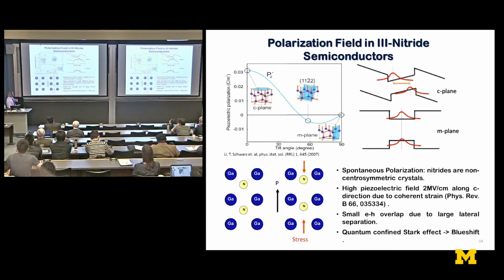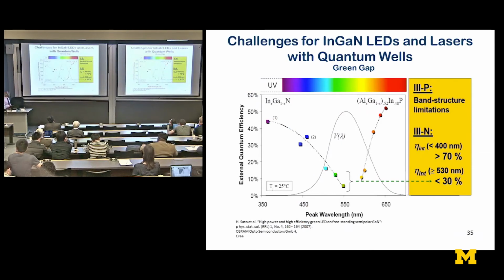It also, as you inject, there is screening of this piezoelectric field, and that leads to a blue shift of the emission wavelength, which is also a bit of a problem. In addition to that, in quantum well devices, which are all used in the industry to make these blue lasers and other blue LEDs, as they add more indium, this leads to compositional non-uniformities. And in fact, what is seen is a 0.6 to 0.7% decrease in efficiency for every nanometer of wavelength shift. And this leads to what is known as the green gap in the industry. So beyond green and beyond, with quantum wells, you just can't do it.